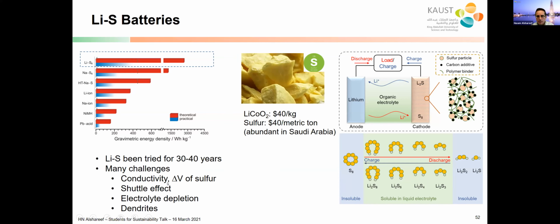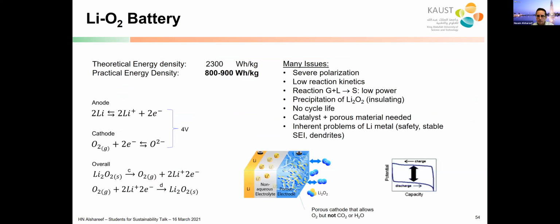So you need to add conductive material, and then you lose active material in capacity. Sulfur has large volume change. There's this so-called shuttle effect. Some of the compounds formed during the operation of the battery dissolve in the electrolyte. They go coat the cathode. They also react with the electrolyte and make it a solid. And then also you have the dendrites that could potentially form in the lithium. So this is a promising battery with a lot of problems, really. There are some startup companies that are working on it, but I would not say this is as close as the ones I showed before, like solid state electrolyte.